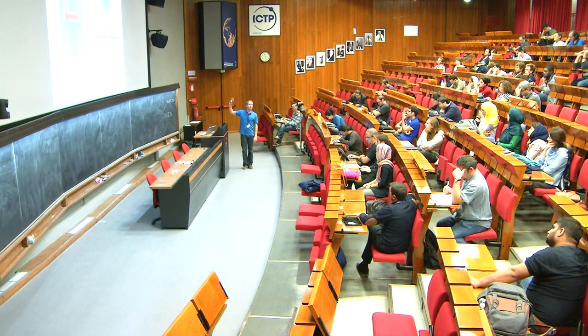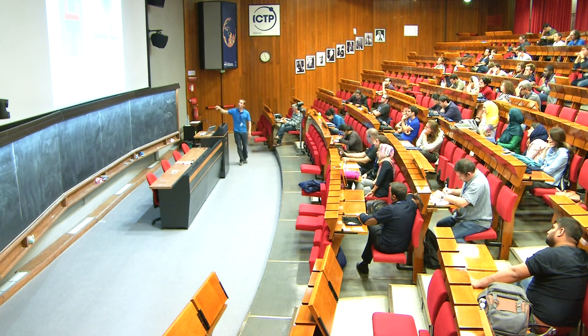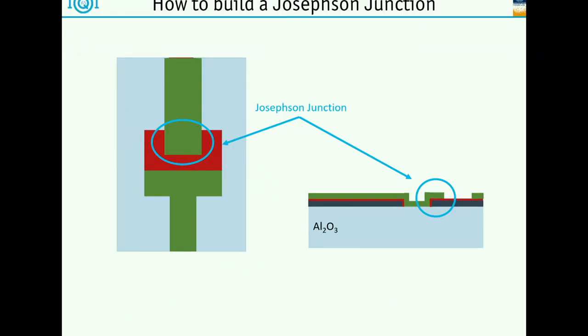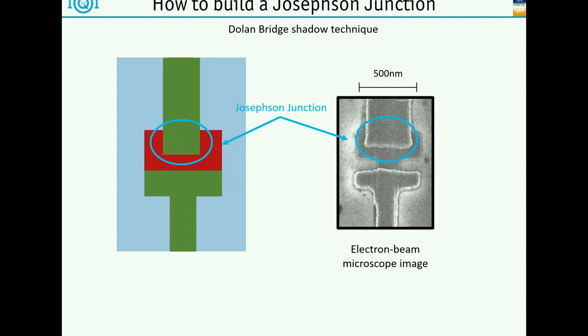What's left is I want to wash away all the rest of the mask, so this remaining PMMA and MMA layer, all the bridge and everything. I do that using acetone, and what I've left then is just these thin films of aluminum with this barrier in between, and right here, this is where I've created my junction. So here's an electron beam image of an actual junction, and you can see it's a very similar structure. Here, down there, this is the bottom layer which has been oxidized. You can see it here. And then on top is the green layer, and the junction is right there.